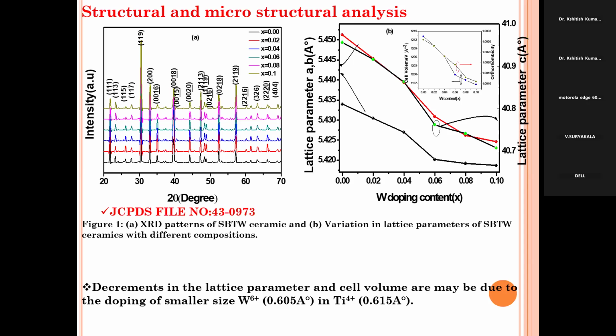But then we did the Rietveld refinement. It is another analysis, and we found the lattice parameters of the material, that is the a, b, c lattice parameters. We found that in the doped samples the lattice parameter gradually decreases. Suppose for the pure one the lattice parameter a is 5.42, then with increasing doping concentration the lattice parameter gradually decreases. And the cell volume also decreases.